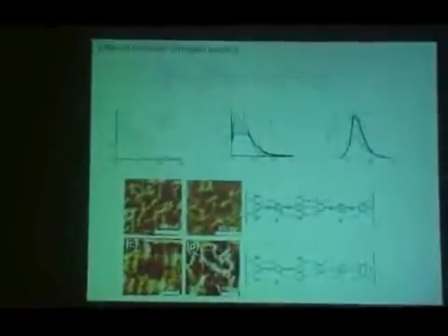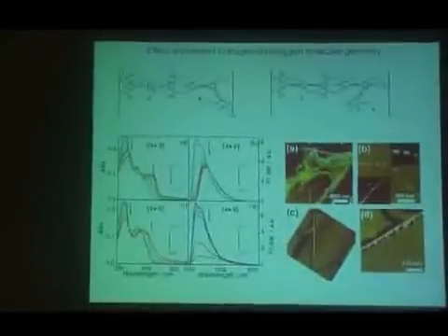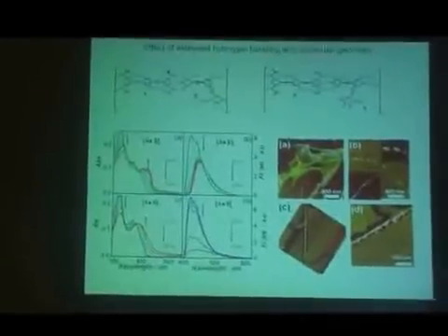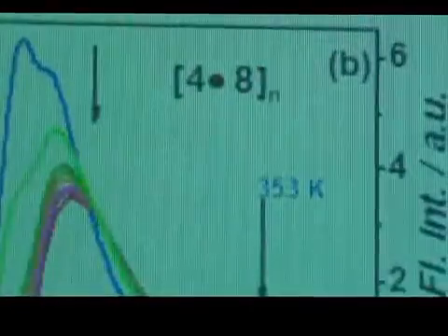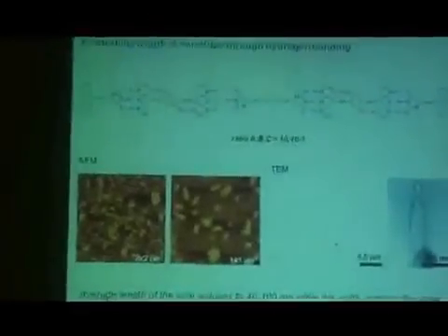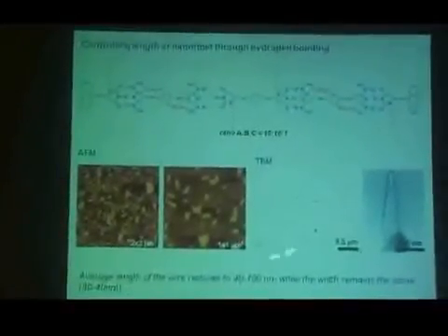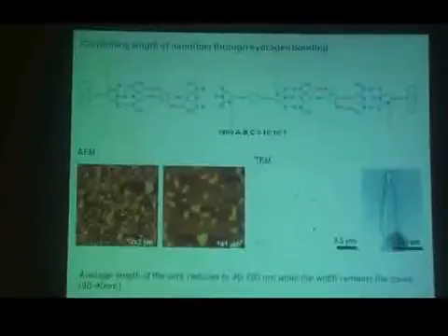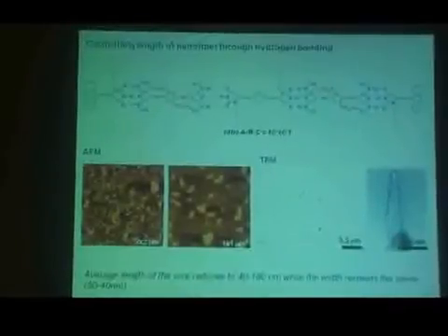So that is what we did, and what we see is that when you use the linear type of molecule, you get a linear polymer and it forms a nanofiber. Similarly, if you change the molecular geometry to a pen-like structure, instead of a linear polymer or fiber, you get twisted fibers. That is how you change the nanoscale morphology with molecular structure. And if you cap it with a different molecule, the size is reduced to a nano-rod-like structure. So by playing with the molecular geometry, what I want to show you is that you can change the morphology of the nanomaterials.